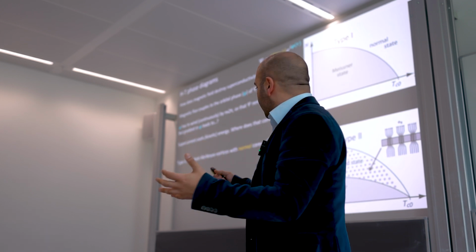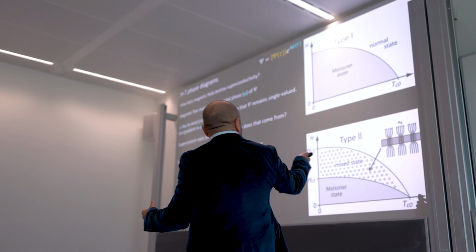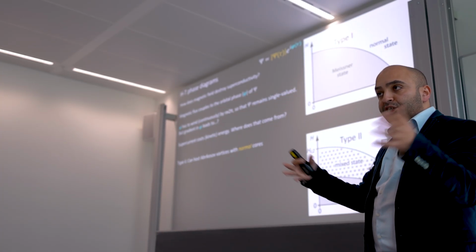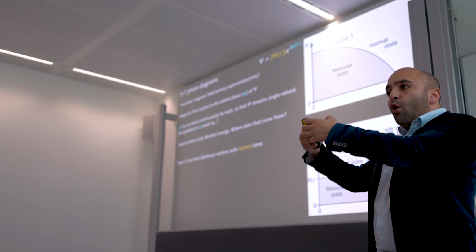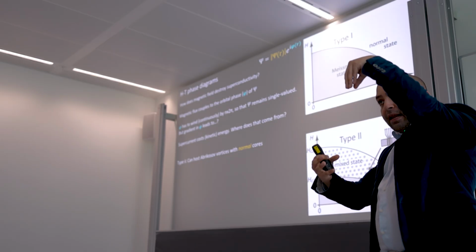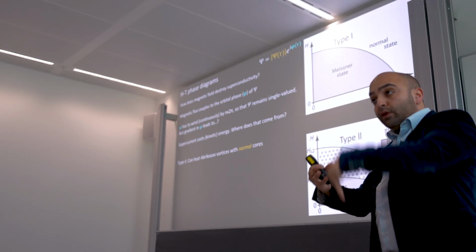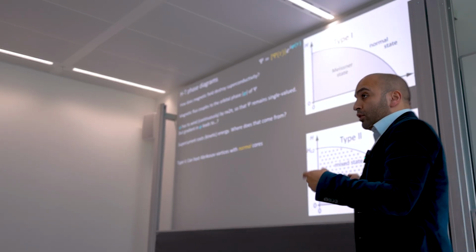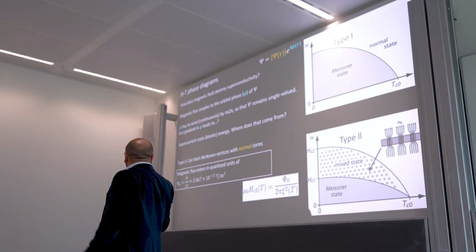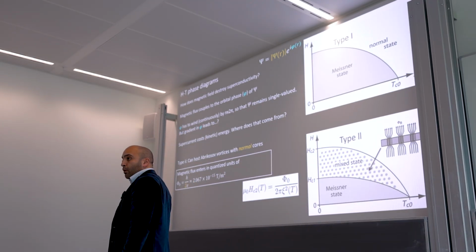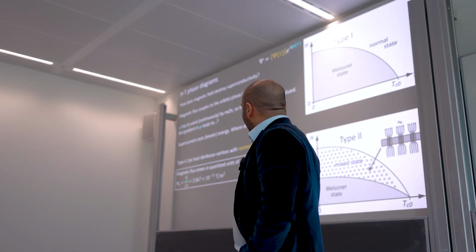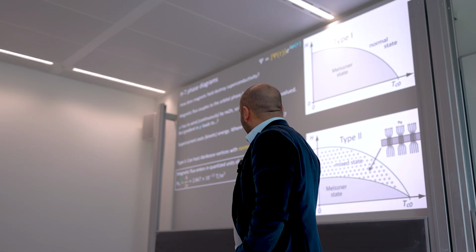So what happens in these materials is that part of the superconductor becomes like a Swiss cheese. Part of it has these holes in it. And then your magnetic flux can actually go through these holes, but it does it in quantized units. And those units are h over 2e, or the magnetic flux quantum. And the 2 actually is because we have Cooper pairs.